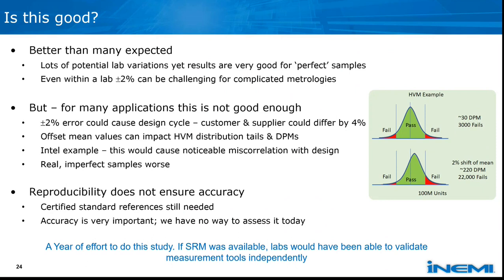But for many applications, this isn't good enough. A plus or minus 2% error could cause a design cycle issue, or it could mean that your customer and the supplier could differ by as much as 4%. And again, this is really for the best case samples. More typical samples are going to have more variability due to issues like thickness variation.